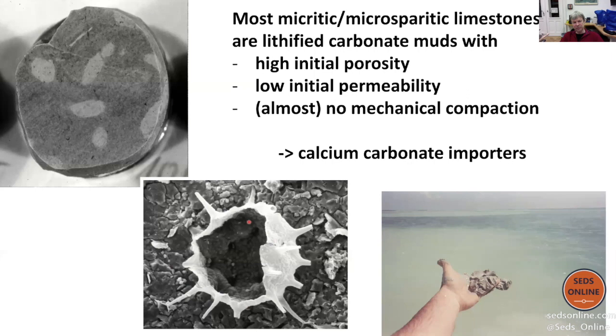It's even nicer visible here in these organic walled microfossils. It's an acritarch here. These fossils are very susceptible to compaction. It's very easy to compact these organic walled fossils. They have very thin walls, but in limestones, they are preserved three-dimensionally. But what does it mean? If we turn a carbonate mud, a water-filled mud, into a limestone without compaction, it means we have to replace the pore water by calcium carbonate cement. Or in other words, these rocks are calcium carbonate importers. And this is important, in fact.